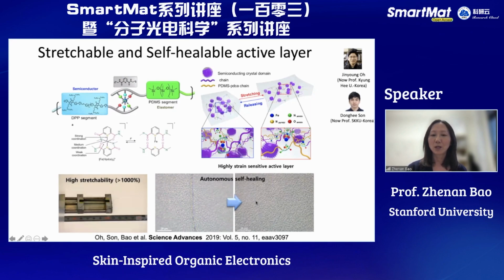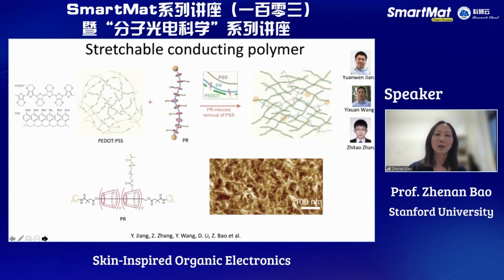And we also showed this with, for example, silver nanowires or nanoflakes, which can have the same mechanism for mechanical healing and electrical healing. For conducting polymer, again, nanostructure is very important. Yi Xuan was a visiting scholar from Tianjin University, who was instrumental in the design of this new crosslinker. We previously know that the PEG groups, when added into conducting polymer PEDOT:PSS, can result in improved conductivity because they induce the aggregation of PEDOT. In some cases, it can form nanostructure.